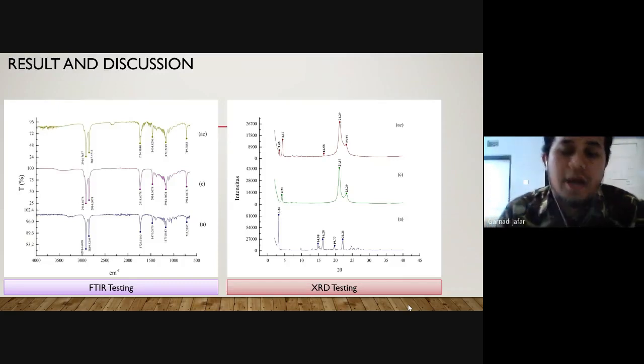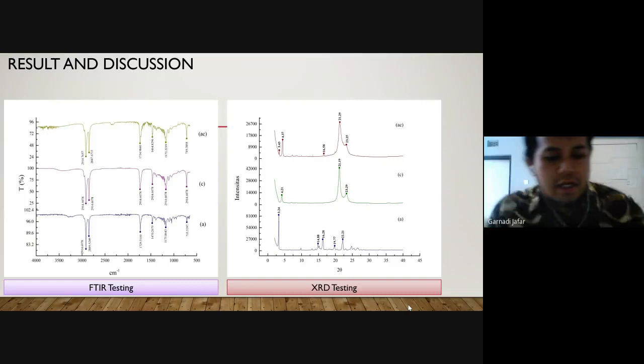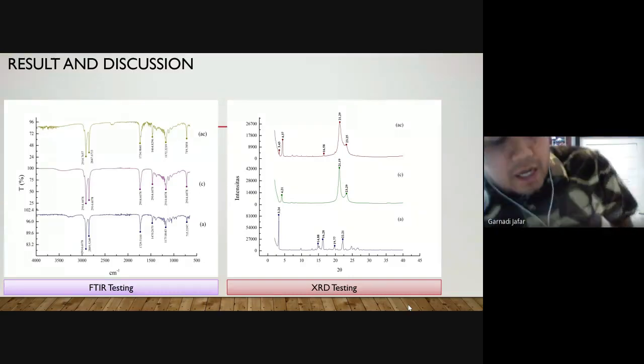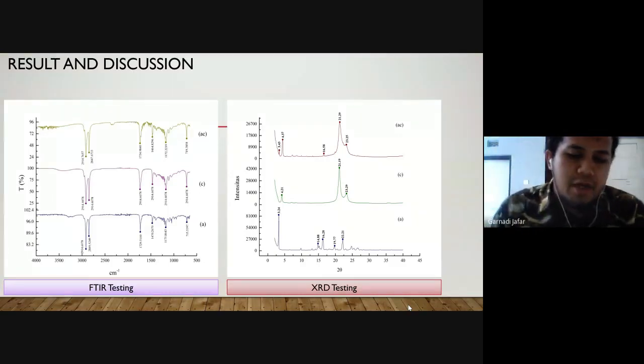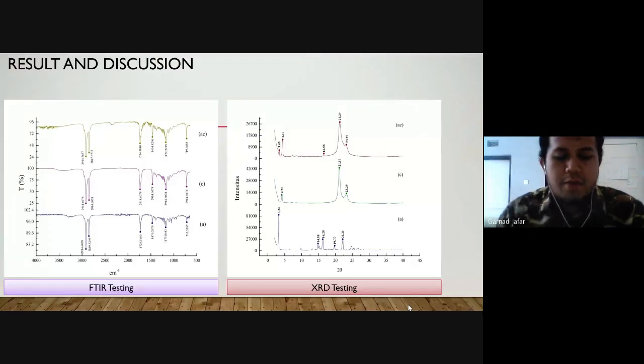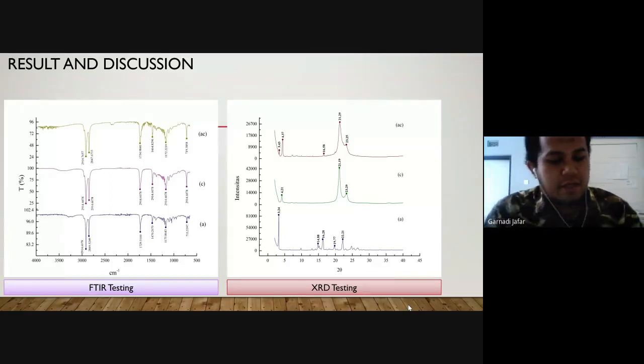And then XRD testing. The next raw material characterization was the XRD test. The adapalene compound image shows a sharp peak as well as a narrow area. This shows that the adapalene compound has a high level of crystallinity. The second image shows the solid lipid compound that has no sharp peak and a large area. This shows the solid lipid has a low level of crystallinity. The third image is the mixture of adapalene and Compritol. The figure shows that the crystallinity level of adapalene decreased after mixing with solid lipid.